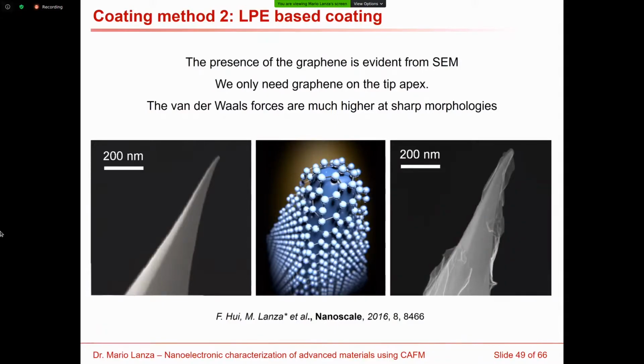And I started to work with my student, Fei Hui, and she found a very nice method, which is to use liquid phase exfoliation. Basically, you just have a glass of water containing graphene exfoliated by liquid phase exfoliation. You immerse your tip, you take it out, and what you observe is what you have in the image on the right. You can really see that the graphene is coating the shape of this tip.